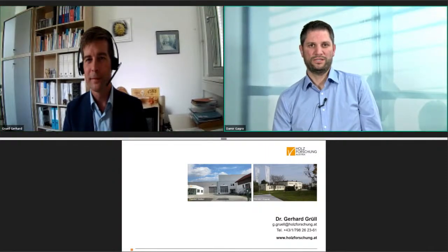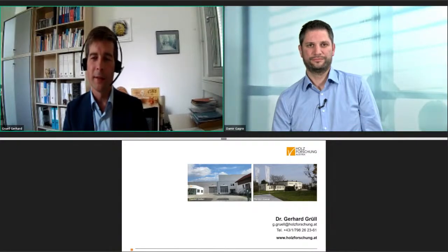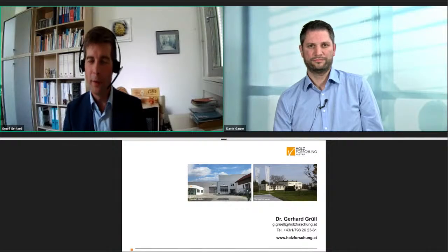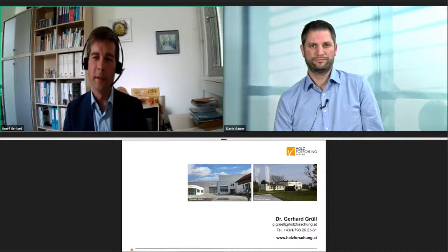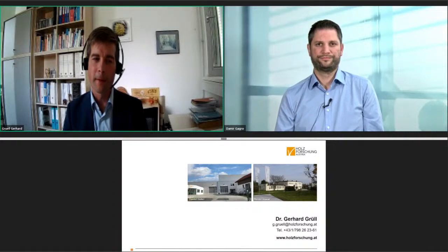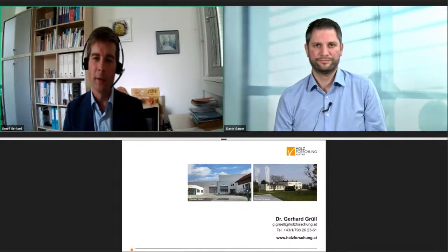Okay, then what is better? HALS in the transparent primer or in the top semi-transparent film? In the end, you will need both, because HALS as a radical scavenger for protecting polymers against degradation by UV light will be needed in the wood to protect the lignin and the cellulose, and it will be needed also in the coating layer to protect the coating polymer. But the pigment helps a lot as well.